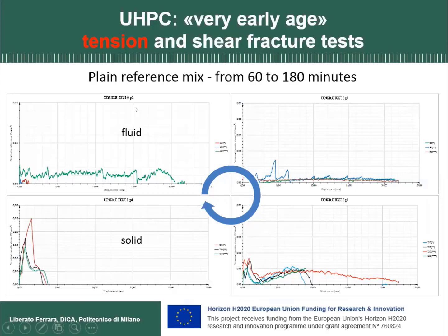You have the first test at 1 hour, where the response is still fluid. Before 1 hour, actually, we were not able to perform any test because the mix was really liquid and flew out of the mold. So you have 1 hour, 1 hour and a half, 2 hours and 3 hours, and you can clearly detect how the results of our test were able also to highlight some fluid to solid transition.